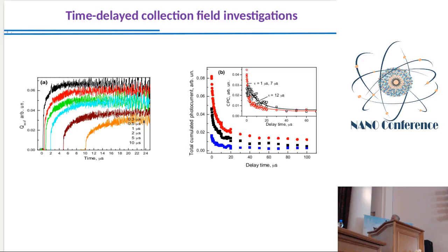And we also see that there is a difference between this rise time. So here is faster, here is slower. So when we generate charge carriers, they apparently find some trap states, and then after application of the voltage, we should extract these charge carriers from the trap states. Okay.